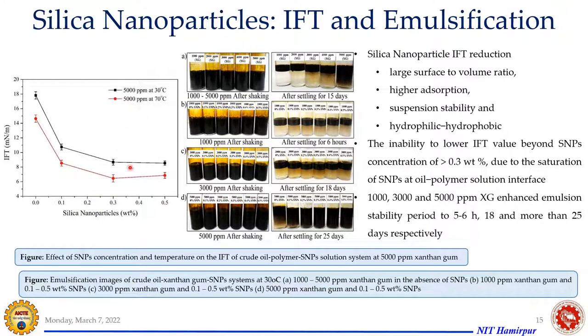IFT, as I told you, so what you can see, this is the condition. This is the polymer at 5000 ppm. And you see when we add nanoparticles to this, the IFT decreases. And this observation was observed at lower temperature and also at high temperature. So a positive output is getting from this IFT, which shows that nanoparticles have the potential to reduce the IFT,